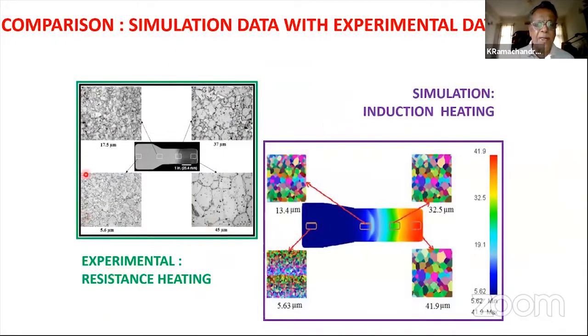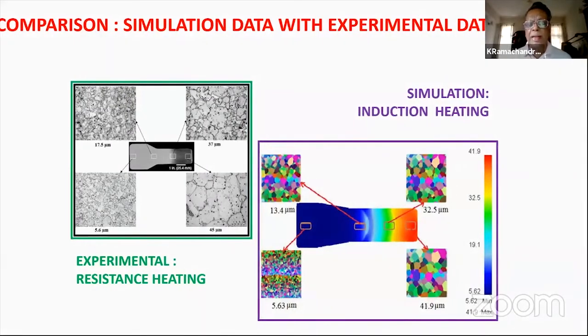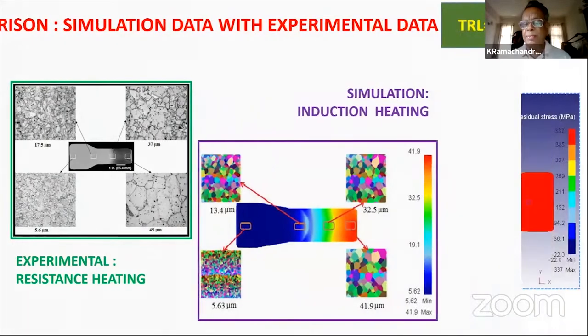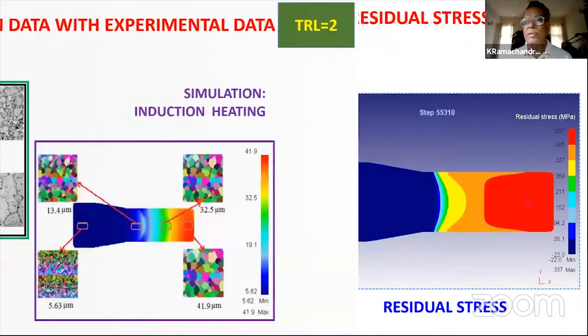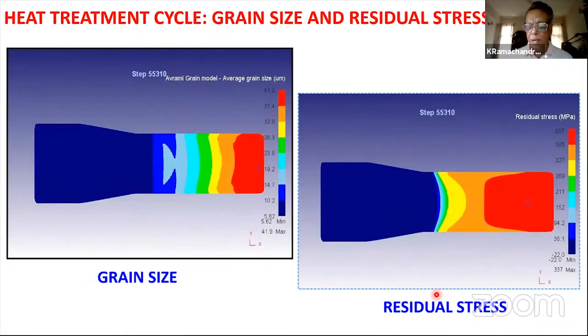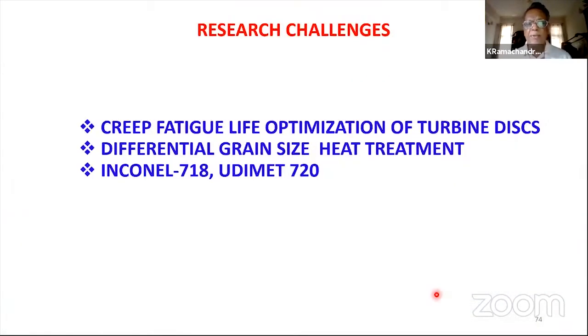For example, if you did an experimental cut up and looked at the microstructure, which is grain size 45 microns at the rim and about 5 or 6 at the bore, we can get the same thing through the simplified induction heating process. You can see it is similar, if not exactly the same. So there is a possibility of getting this through simpler induction heating processes, but there are some residual stresses which creep in. And therefore, we must develop technologies for creep fatigue life optimization of the turbine disk.